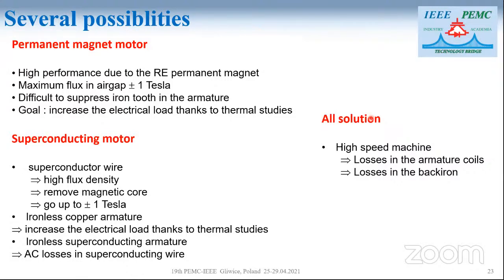So we have several possibilities. One of them is to use permanent magnet motors, and in this case, we take advantage of the high performance due to rare earth permanent magnets. It's a big area of research. But the maximum flux in the air gap is about 1 Tesla, and it's really difficult to suppress the iron teeth in the armature due to the difficulty of increasing the magnetic field created by the inductors. The main risk is that the magnetic field on the armature coils decreases a lot if you remove the iron teeth. So the main goal is to increase the electric load, thanks to a lot of thermal studies, to be able to remove a maximum of losses and increase the current density inside the armature coil.